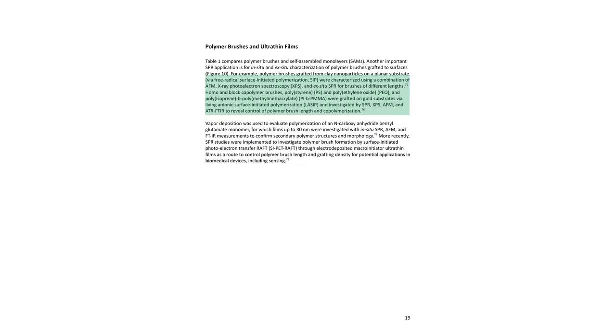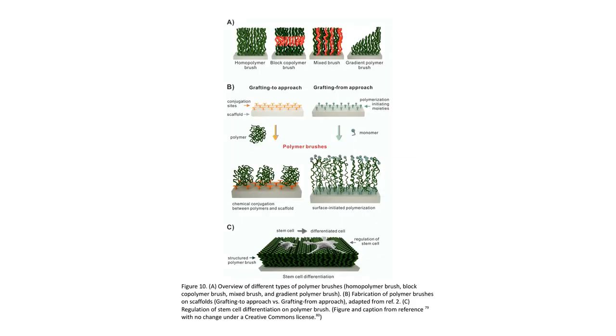The authors have used SPR, both in situ and ex situ, to characterize the growth of these brushes from surfaces, for example from clay nanoparticles or directly from gold substrates, using various surface-initiated polymerization techniques. This control over polymer brush length and grafting density is essential for their potential use in biomedical devices and sensing. A diagram in the paper shows how these brushes can be fabricated either by a grafting-to approach, where pre-made polymers are attached to the surface, or a grafting-from approach, where the polymer is grown directly from initiator sites on the surface. These structured polymer brushes can even be used to regulate the differentiation of stem cells.